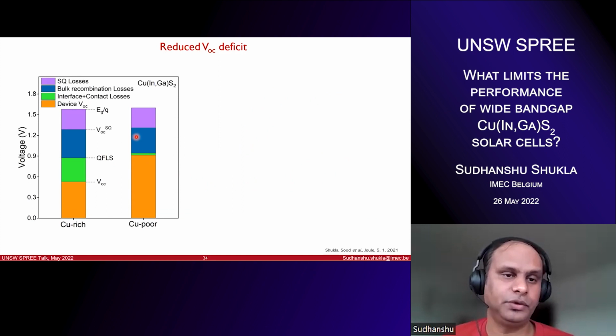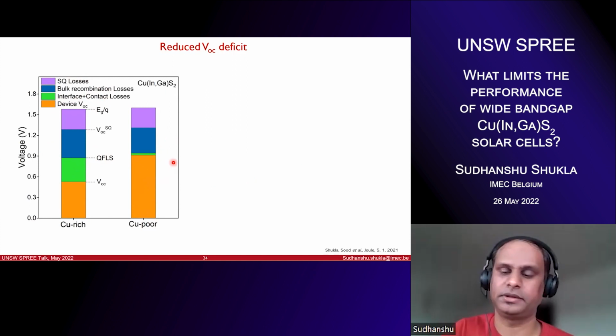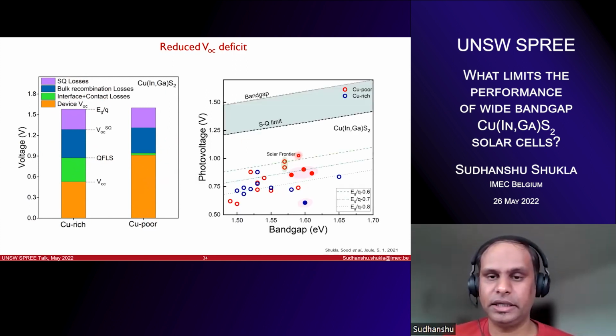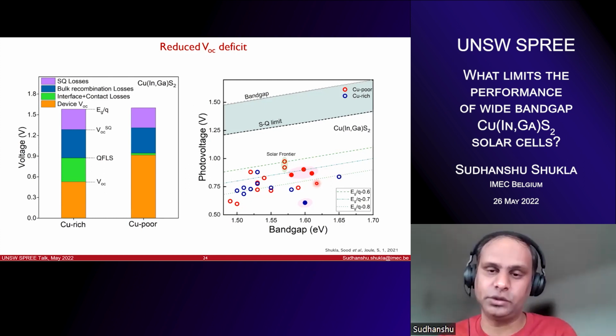And if you put that in the perspective of losses from various mechanisms, we have improved substantially the interface recombination by replacing cadmium sulfide with the zinc oxysulfide, thanks to the copper poor absorber. And we have also improved some bulk recombination by reducing the deep defects. So this blue bar is actually less in the case of the copper poor absorber. And that actually puts us in the literature somewhere here. This is the regime of interest. As I said, if you want to make a tandem cell with a wide bandgap top cell, this is the area of interest. And you want these numbers to be as high as possible, somewhere here, not here. So this plateau is still frustratingly limiting us, but that's a good sign that we are improving here.